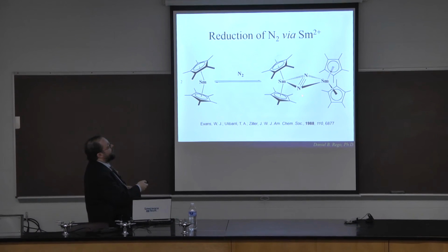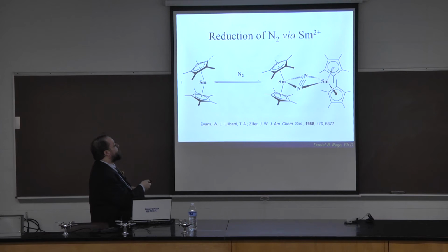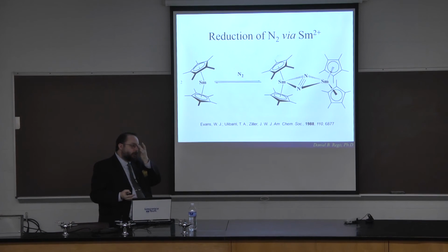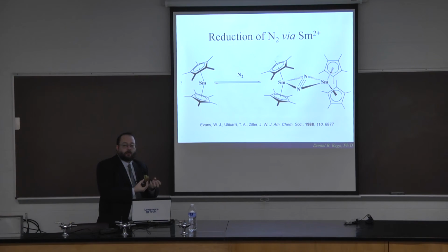What I think turned out is that we actually had the normal 1.25 distance, but we also had a slight impurity of oxides and oxygen here. And it is known that a slight impurity can give an anomalously short bond distance. There's an infamous case called the bond stretch isomer, where they had 2 different colored crystals. They seemed the same except the chloride seemed to be at 2 different distances. It turned out that some of the time that chloride was actually something else that was much shorter, and simply because the chloride is there most of the time, it resolved as a chloride, but at a shorter distance. So this crystal was proof of that, a slight impurity giving you an anomalously short bond distance. And I've actually seen this in other compounds, as well as with carbon-carbon distances.